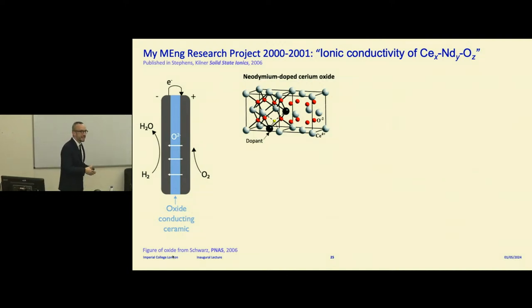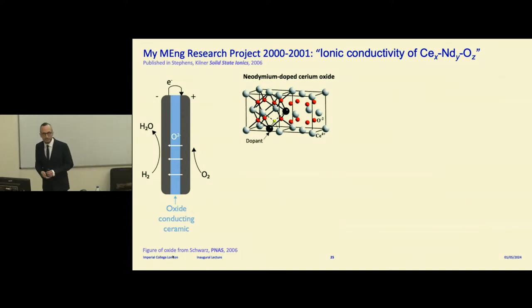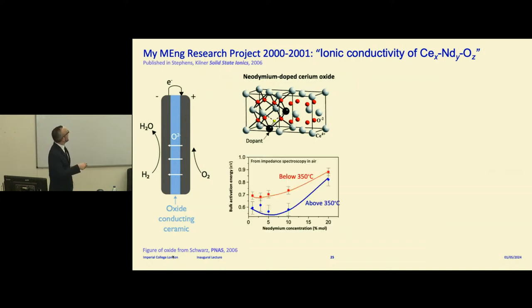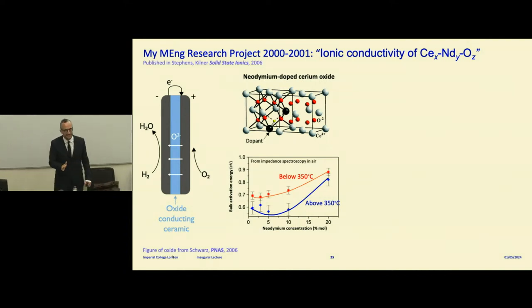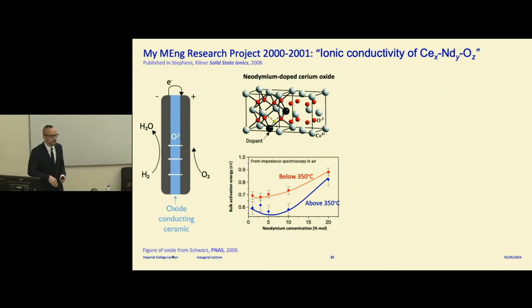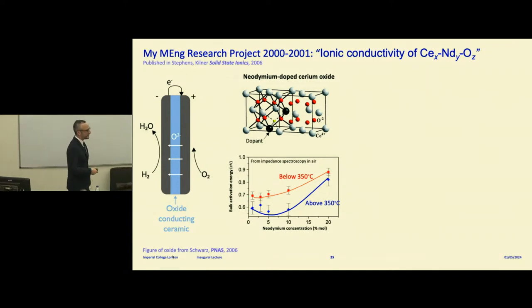Usually they work at several hundred degrees Celsius. There are a lot of people interested in trying to get the temperature lower for many practical reasons. So what you want is to get the oxygen to move as easily as possible. Essentially what I did was study how the activation energy for oxygen transport changed as a function of the amount of neodymium, the second metal you put in this oxide. The activation energy tells you how big the energy barrier is for the oxygen to jump around. So the higher the value, the more difficult it is.